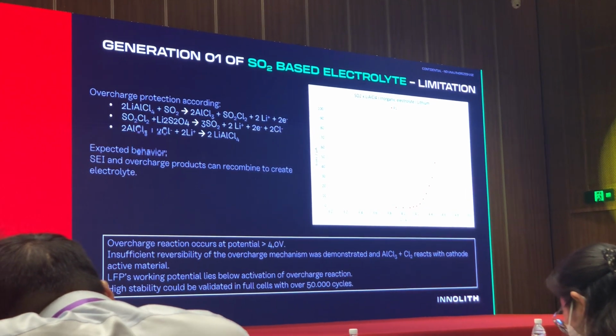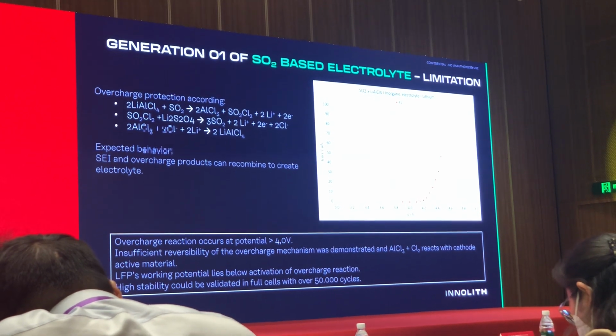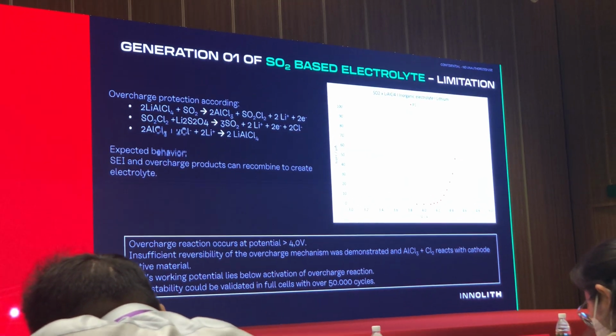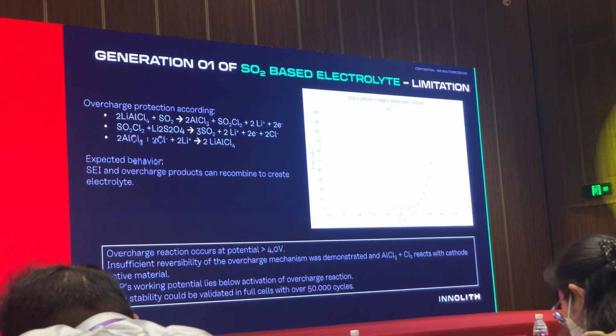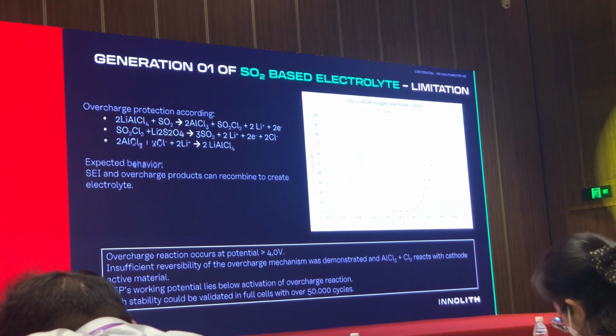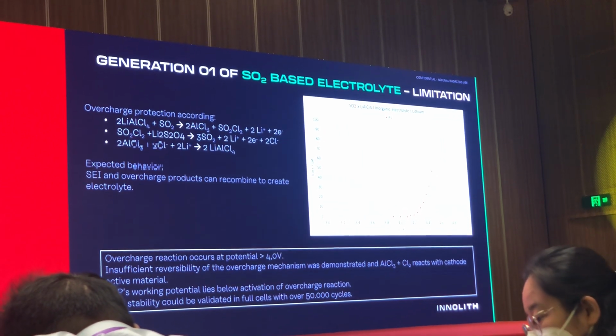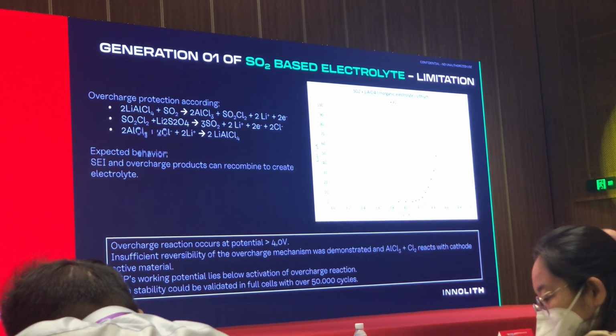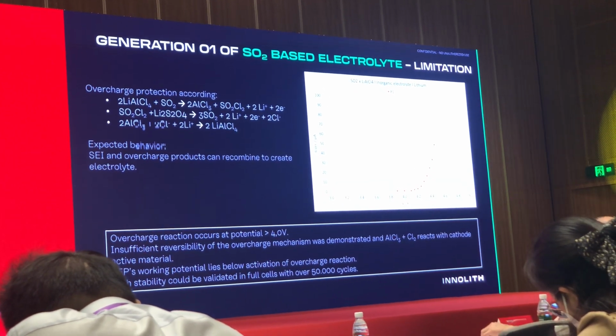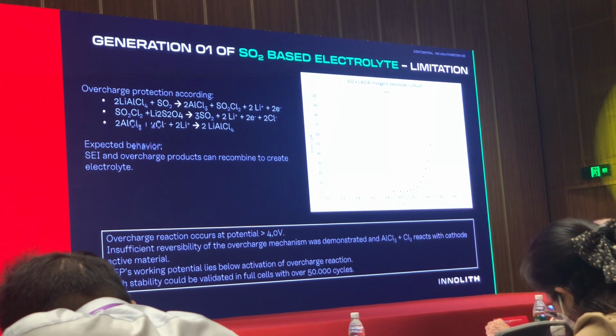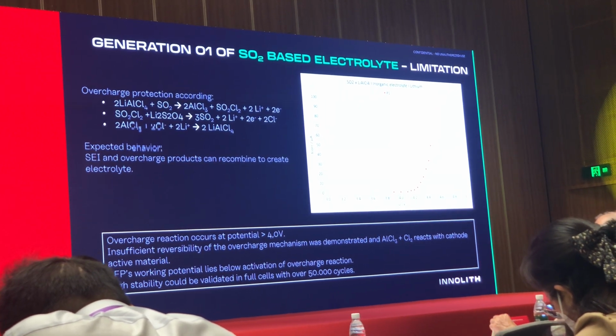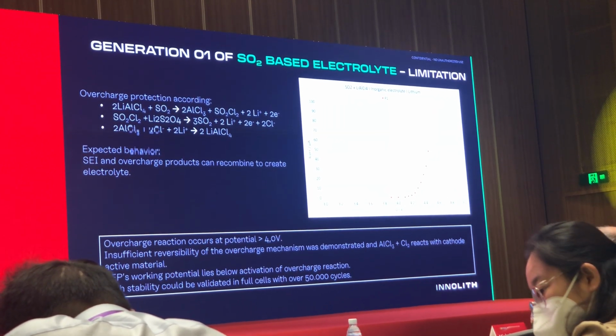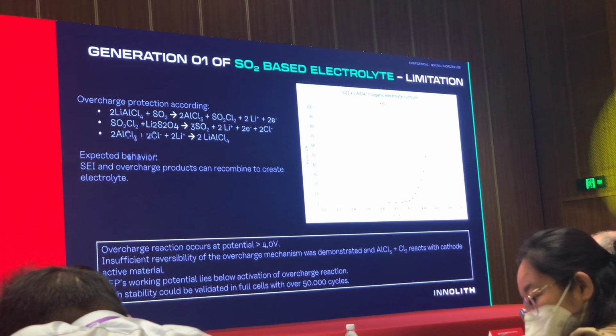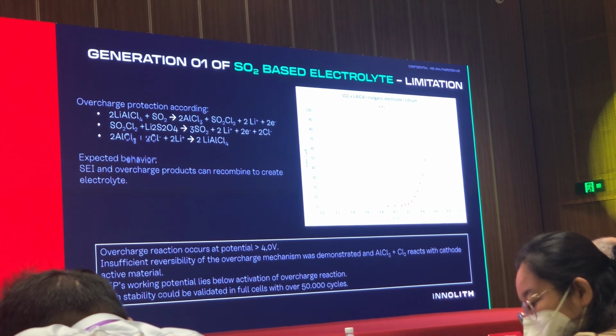chemically, so we had to use cathode material which had a working potential below the oxidation. That means we could pair this electrolyte with the LFP graphite system and reach a highly stable system. More than 50,000 cycles could be validated, and it was produced at mass scale for ESS application.